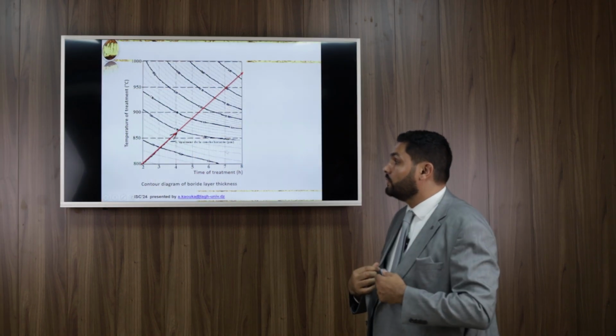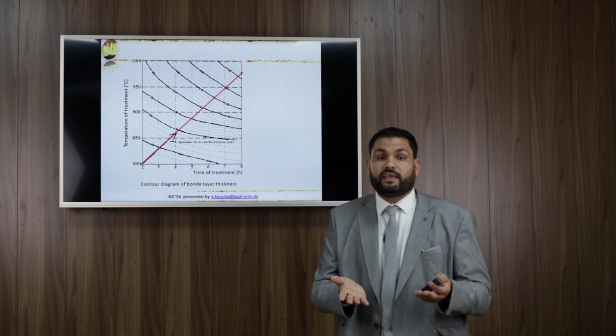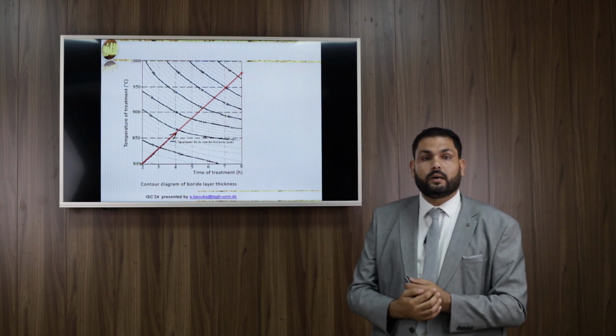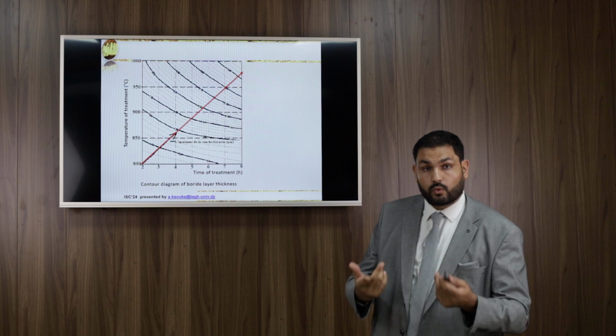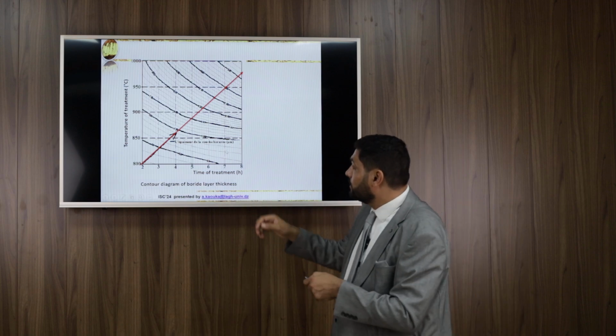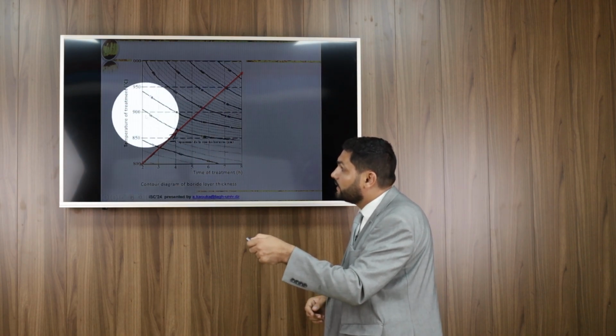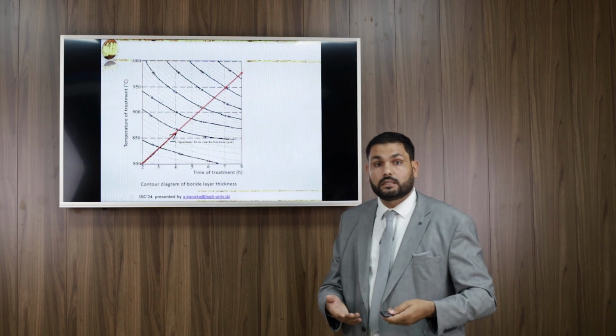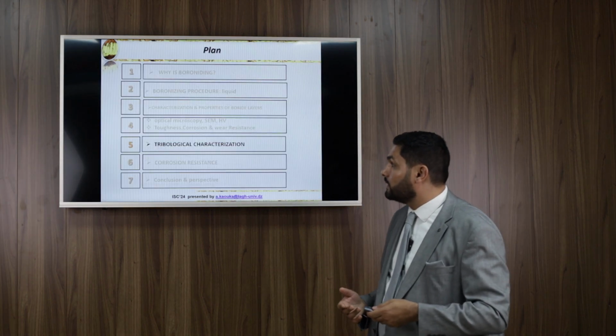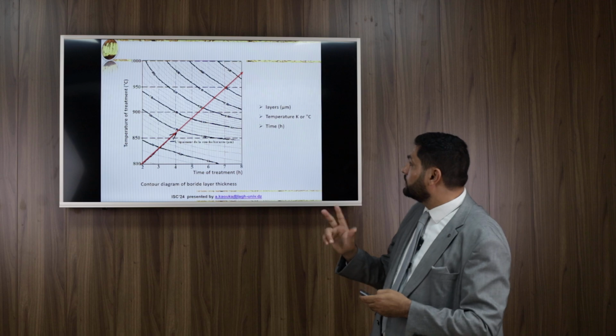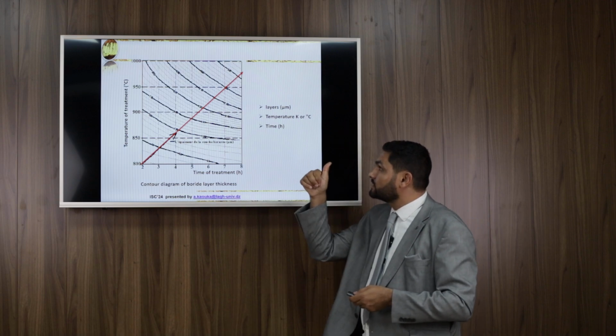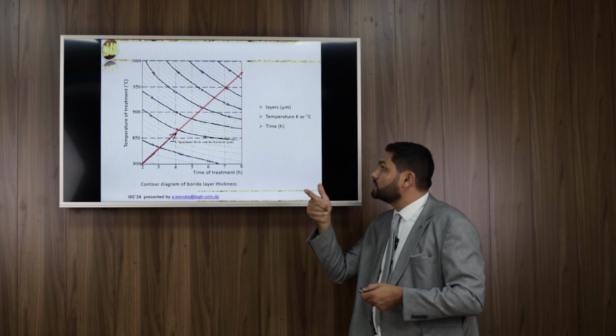And also, if I want a thickness of about 150, you can use, for example, this temperature, 900, and a time of 4 hours, and you can obtain 150 thickness. So we play on three factors: the thickness of boride layers, temperature, and time.